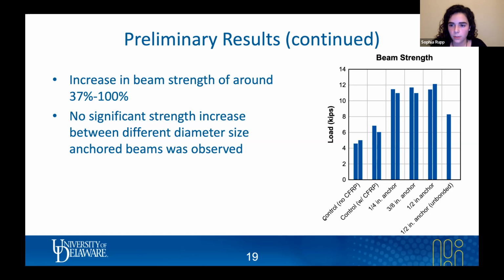And one thing that's very interesting to point out here is that we didn't see really any significant differences between beam strength for the differing anchor sizes. That's not something we expected to happen, and it's something that will be interesting to see if that still holds true for the accelerated condition beams.